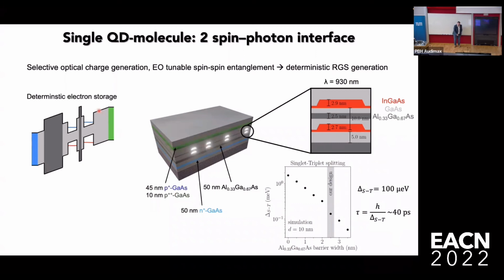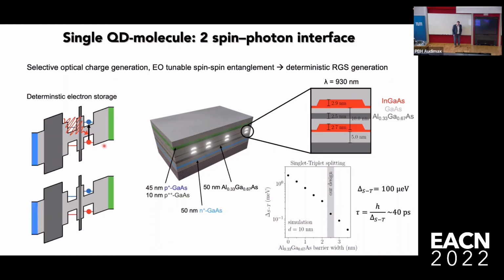Well, this is what the band diagram looks like. We come with a laser pulse. It's tuned to one of the exciton transitions. That creates an electron hole pair, and the hole here can tunnel out. So there you see it, it's tunneling out, leaving just the electron behind. That's us creating the first electron. And then we can do the same thing again to place a second electron inside this thing. And then we have our two electrons, and we can control the energy of the two levels to allow them to couple or not couple.